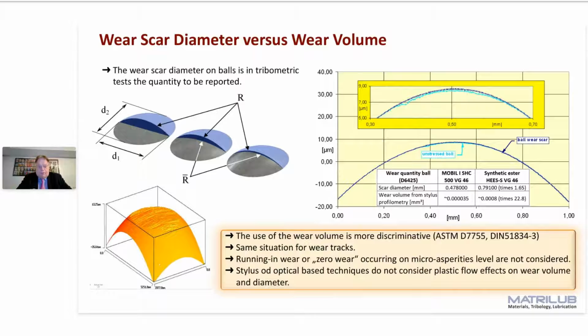So the biggest point is longevity, and longevity means you have to measure wear. The situation for long is that different types of test equipment, or test procedures, ask you to show or to report the wear scar diameter. You see on the left 3 wear scar diameters, and the blue shows you that the shape, even the diameter, for all 3 is identical. The real abraded volume can be completely different.